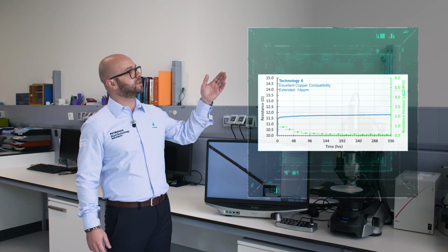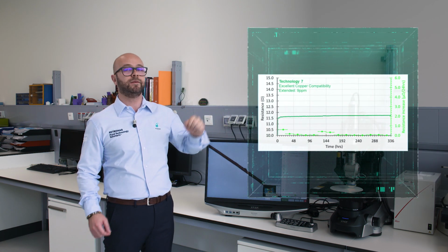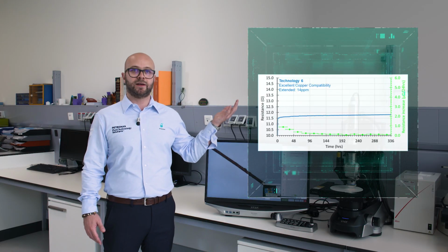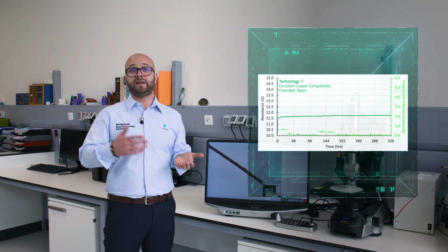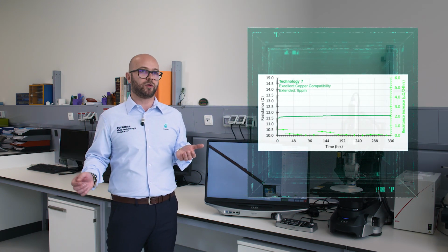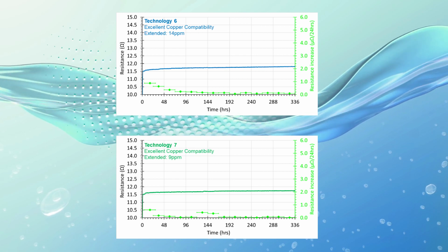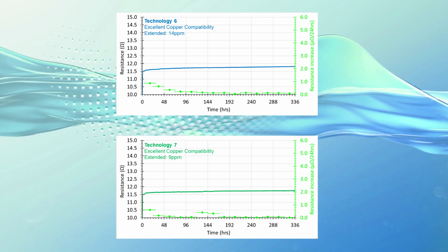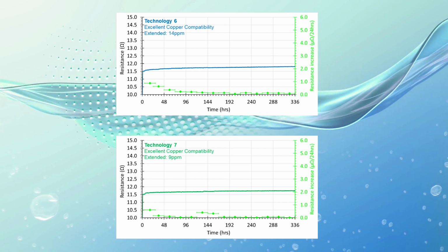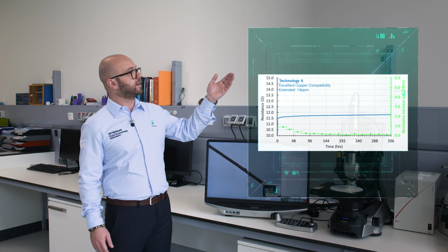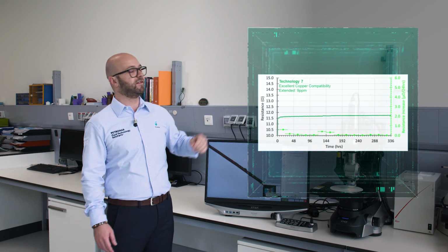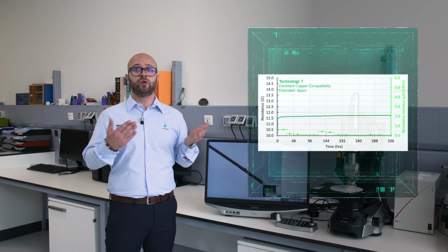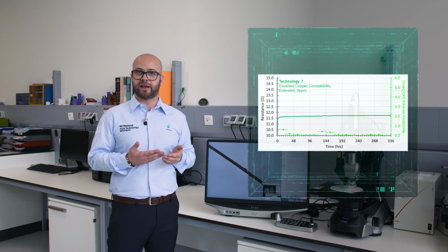Moving to technology 6 and technology 7, situation is extremely better from the point of view of corrosion resistance. So we are losing some performance in load carrying capacity, but this is balanced by the excellent copper corrosion protection. In fact, the curve in the two plots is completely smooth, and the rate of resistance increase is negligible for technology 6 and in particular for technology 7, which is close to 0 over the time. So the two technology doesn't have any issue to reach the 336 hour end of test.